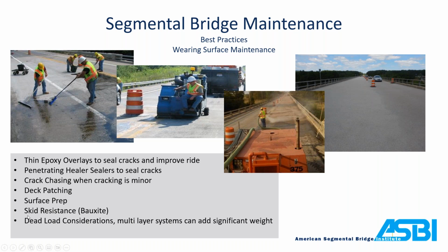And one thing to consider before going full blown with a thin epoxy overlay is what it does to the dead load on the bridge. Some of the older segmentals are right there on the cusp of rating factors of 1.0 or just above 1.0. And you do add quite a bit of weight if you go with the 2-coat thin epoxy overlay, with the amount of aggregate that you add, and it may be enough to push you over where your rating factor drops below a 1. So it's something to check before you jump into a thin epoxy overlay.